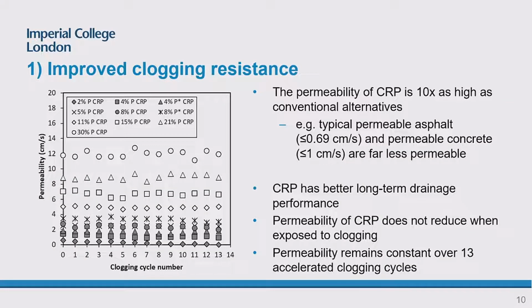So just to show the clogging resistance performance of this pavement, we have tested this pavement of different porosity between 2% to 30%, and we exposed it to 13 cycles of sediment exposure, the same way as the conventional system. And you can see the permeability is more or less constant throughout the exposure to sediments, which is very promising for us. And typical permeable pavements are lying within this range, the lower end. So the permeability is 10 times higher than what you would expect in conventional permeable pavements. And the added benefit is that it can keep that permeability over time.